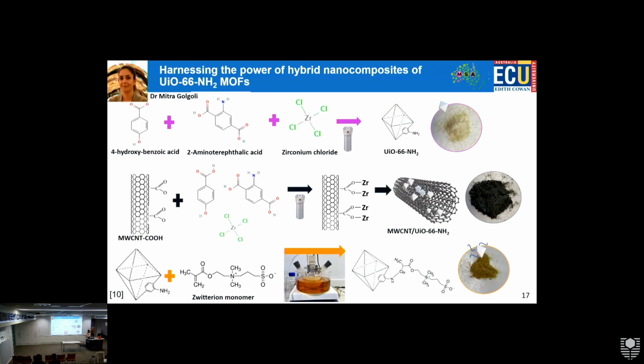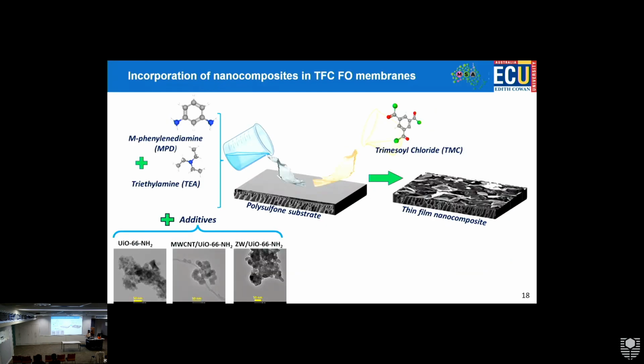In this one, the same zwitter ions that Jawad used were added on the surface of these MOFs through radical polymerization, basically, and then these were also compared in terms of the efficiency. These are the TEM images of the particles here. We use dry samples, so they are aggregated, but in the solutions they were not aggregated, confirmed by dynamic light scattering. But it clearly shows the formation and the integration, for example, of the carbon nanotubes and MOFs together.